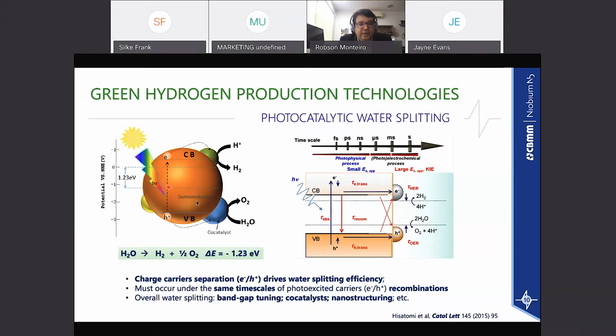the sunlight reaches the photocatalyst and makes this charge split of electron and hole, this phenomenon in time scale is very, very fast. The electron that's generated in the material is separated from the hole. It's typically in the time scale of femtoseconds, very, very fast. And for you to use the electron in photocatalysis and the hole in order to drive the water splitting, the transport of the electron and hole to the surface of the material should also be in the same time scale